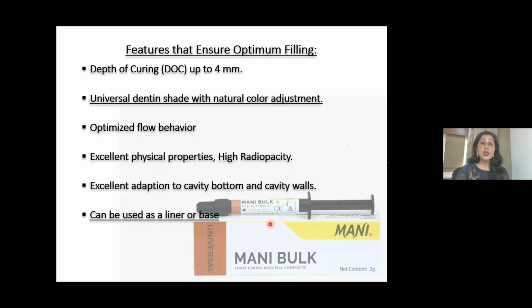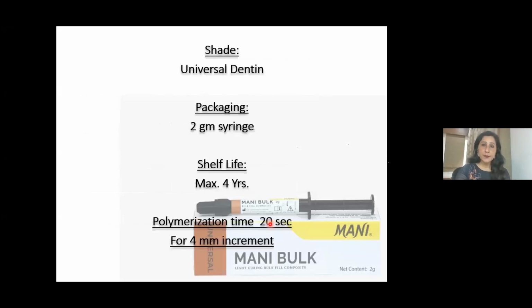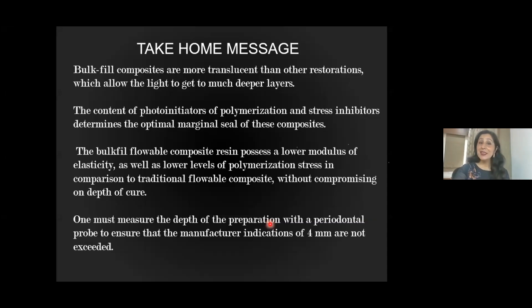Mani Bulk can be used as a liner or base also. It has a shelf life of 4 years. That's good. The polymerization time is only 20 seconds for a 4 mm increment. So this makes your life simple. Now, the take-home message is that bulk fill composites are more translucent than other restorations, which allows the light to get to much deeper layers.